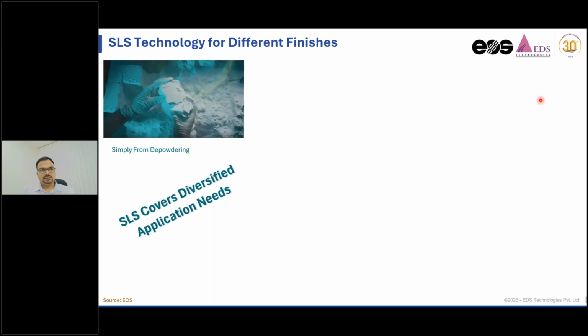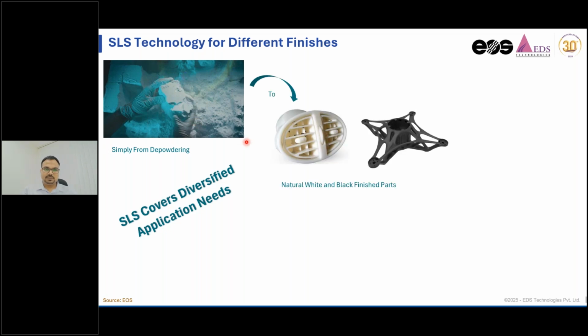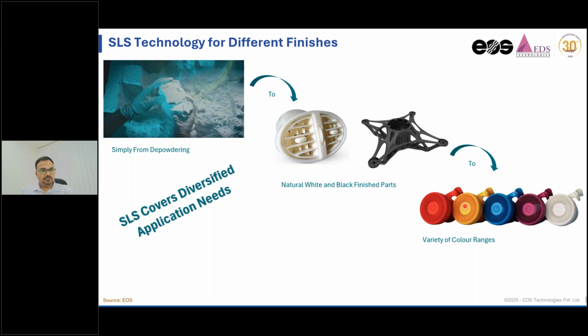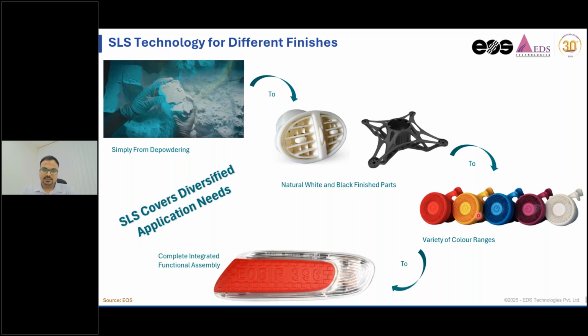What finish is achieved through the SLS process? Right after you get your part printed, you have to take out the cake along with the powder and the component, which we call unpacking. So we take the component out of the powder bed, and this is the finish achieved right after the process. If you are okay with monocolors, white and black, the SLS parts are directly usable at first moment. And if you want any further aesthetics, you can even dye them, paint them, and coat those surfaces so that they become aesthetically more appealing. In any case, SLS parts are being used in industry for different purposes, whether the component is needed for aesthetics or styling, functional need, or testing.